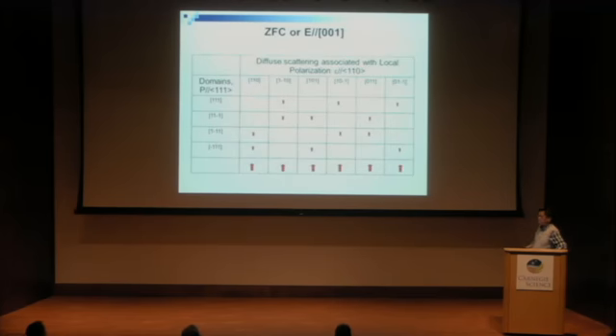Let's see how we use this model to explain our result. We have 4 different kinds of 111 ferroelectric domain, and each is coupled to 3 local polarizations perpendicular to it. In the zero field cool, the population of each ferroelectric domain is almost similar, and so the contribution of each 110 type diffuse scattering is also similar. So they show on average similar 6 different types of diffuse scattering. And if we apply a field along the 001 direction, it has no preference for a certain ferroelectric domain, so the population will stay similar and nothing changes. So the 001 field has no effect on any of the 6 110 type diffuse scatterings.